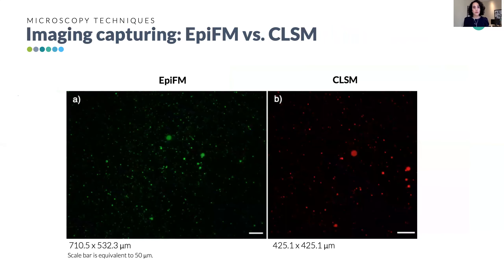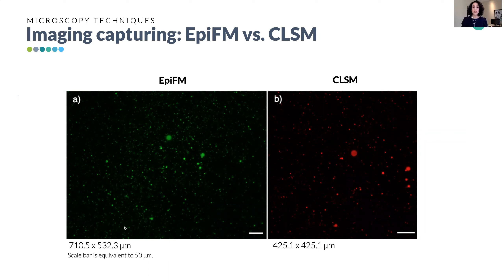After immobilization, we compared images from the two techniques — epifluorescence and confocal. We identified that epifluorescence was the most convenient because it captures a larger area of sample in each snapshot and does not have the saturation issue that occurs in confocal microscopy. From then on we used only epifluorescence.